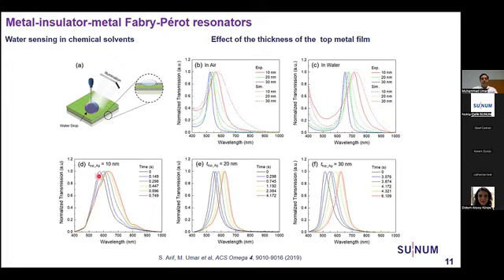So in this case, if the thickness of the top layer is 10 nanometers, the response time of the device is very fast. If the thickness increases, the response time gets slower. This is because if the top metal layer is very thin, there are many more pores, and maybe they could be bigger. That's why the response time is fast.